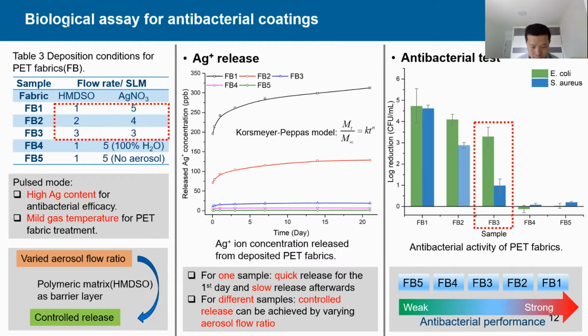A fast release of silver is observed on the first day for FB1, FB2, and FB3. Afterwards, a slow release of silver ions. The initial fast release ensures antibacterial protection in the early stage, which is the most essential stage for infection risk. The initial burst release of silver can be attributed to silver near the surface in the coating, especially for the pulsed mode